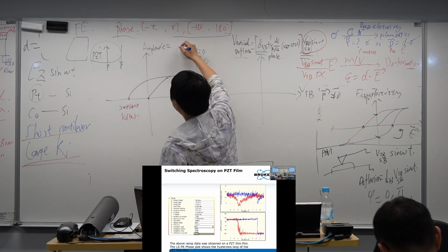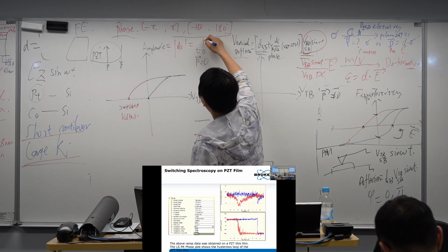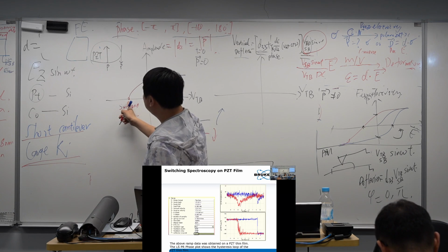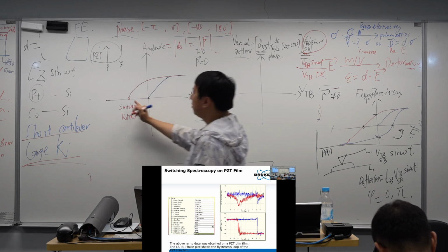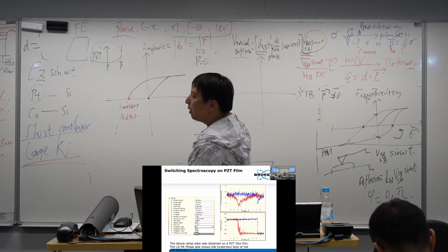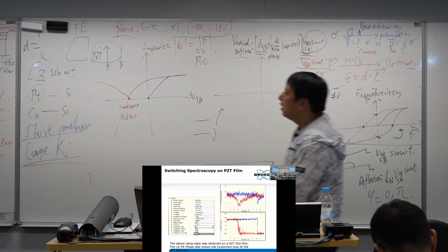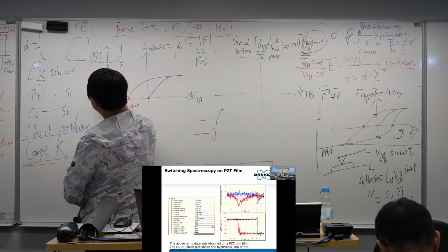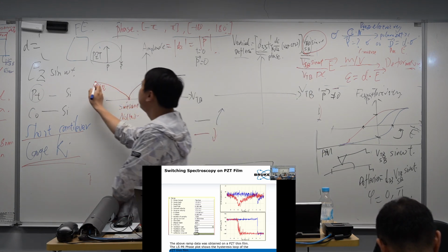The amplitude is actually the absolute value of d33, or the absolute value of polarization. So my polarization goes down, but my amplitude cannot go down. If we consider this line, it should be something like this, but as an absolute value, so it goes up until it reaches 100% facing down. And then the increase will be slow.